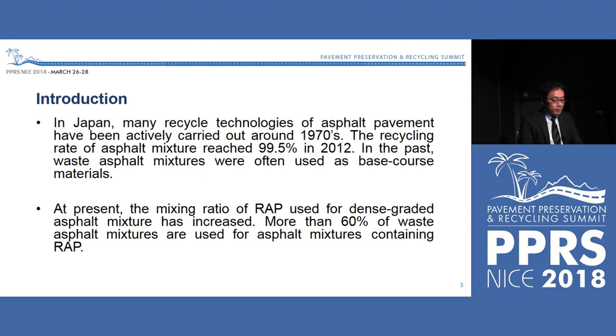First, let me mention the current situation of today's Japanese asphalt pavement recycled technology. The recycle ratio of asphalt mixture reached 99.5% in 2012. In the past, waste asphalt mixture was often used as base course material. At present, the mixing ratio of RAP used for dense graded asphalt mixture has increased. More than 60% of waste asphalt mixtures are used for asphalt mixtures containing RAP.